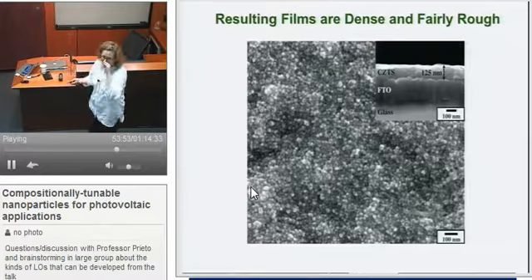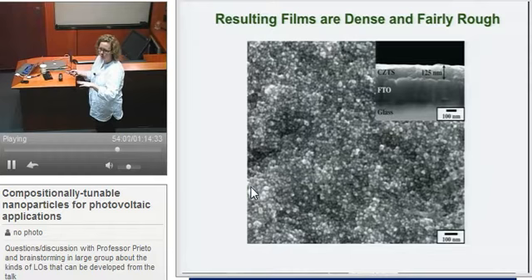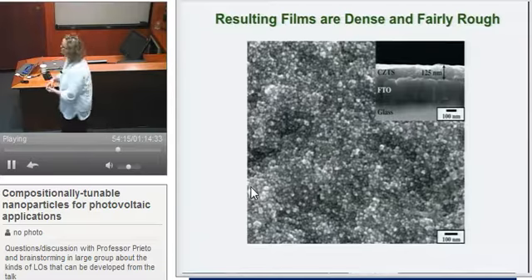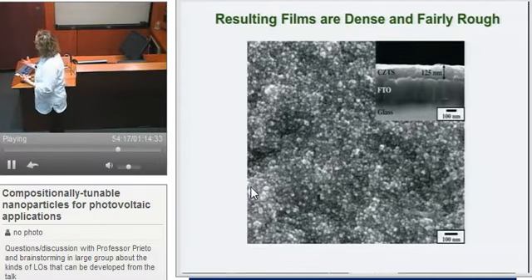This is what they look like. The top is a plan view of one of these films. Note that it's pretty rough, which is good. It looks kind of like black velvet, so it doesn't reflect light well. It absorbs it, which is great. The cross section in this particular case shows glass, fluorine doped tin oxide, which is our current collector, and then about a 125 nanometer thick film. So we can study a lot of electrochemistry as a function of thickness.